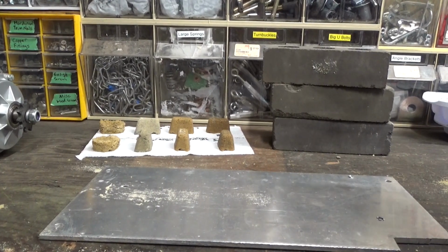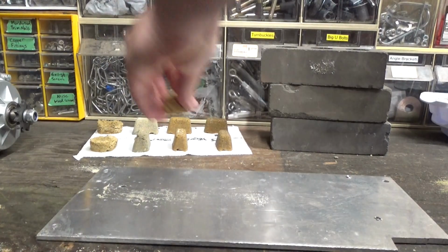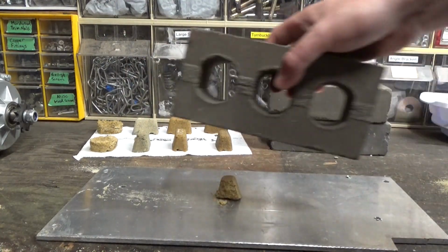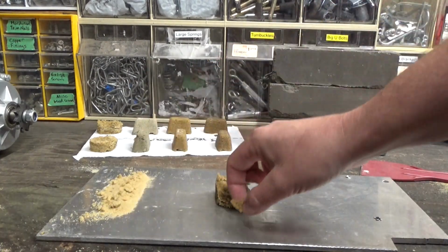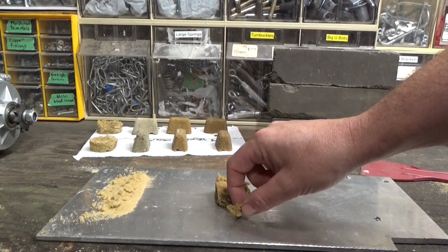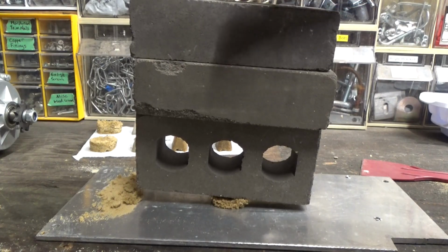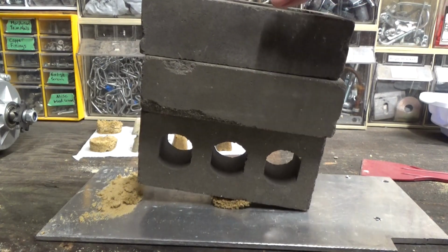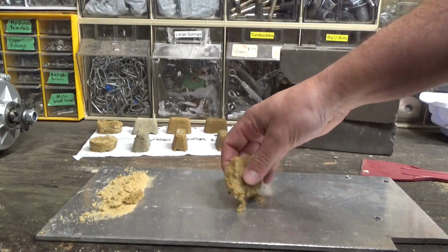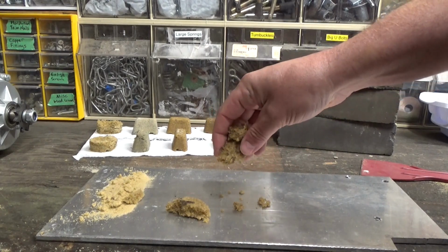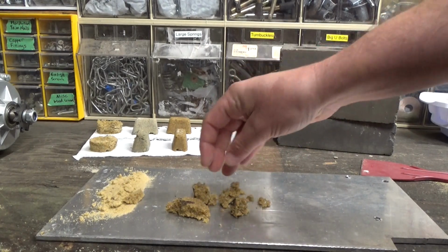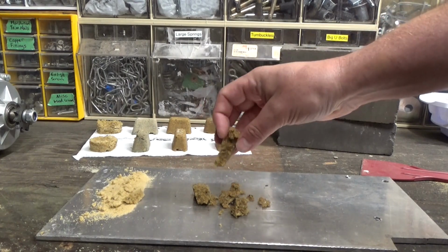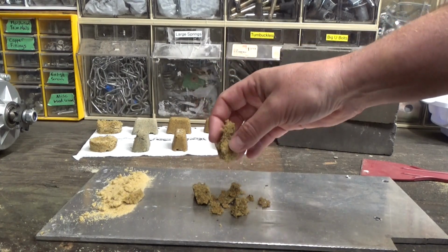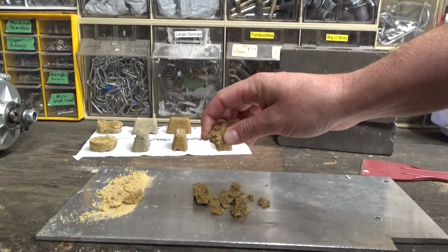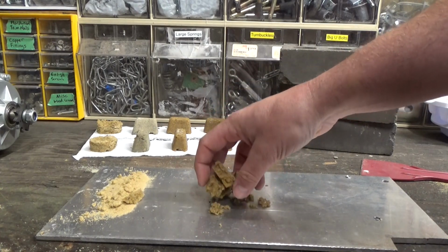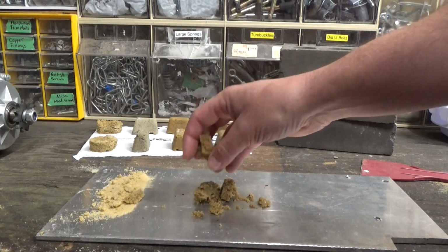Now we're testing the ones that went through freeze-thaw. What's left of number 1, I don't expect much from this. Number 2 has suffered a little more damage while it thawed out. So number 2, after freezing and thawing, has lost quite a bit of strength. It only supported about 2 bricks. That was the hot glue, and I think what happened is as it thawed, it actually warmed up in the sun, and so the hot glue content has remelted in there.